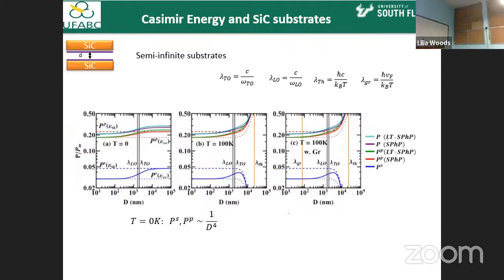Again, look at Casimir, after understanding the material. If I have semi-infinite substrates, like the one I have drawn here, and we cover them in graphene or not, look at the interaction. And we have now not only the thermal wavelength, we have the graphene characteristic wavelength, but there are also two other wavelengths that are associated with the longitudinal and transversal modes. Nevertheless, with all this complexity, we see not really anything interesting. At small distances and large distances, there is some kind of a transition, but it doesn't really matter what kind of substrate surface.